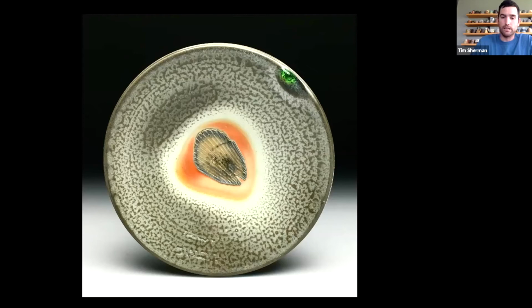They get really heavy sodium buildup. They get a lot of carbon trapping because we're able to stoke the front of the kiln, which will have an impact on what happens in the back, obviously. And you can get these nice, rich carbon trapped grays. Even this is on the underside of a bowl that would have been upside down in the kiln. So the seashell in the middle is giving that little pink blush from the calcium.